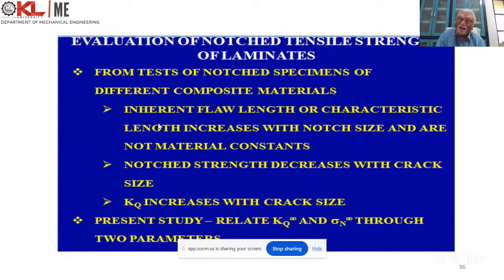So what all the tests have shown is that the inherent flaw or characteristic length is not a material constant. It increases as the notch size increases. Then the strength decreases as the crack size increases. What about the fracture toughness? It increases with the crack size. So what will be happening? Two parameters: one is KQ infinity, another one is sigma n infinity.